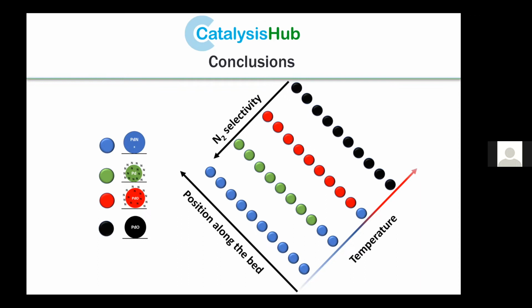Even though palladium nitride is absent from the bulk of the particle, we suggest the presence of a surface nitride structure. And while nitrogen is still present, there is still appreciable selectivity toward nitrogen. As the particle becomes more oxidized, there is a change of selectivity toward NOx product. And at 400 degrees in particular, there is a suggestion that not only ammonia selective catalytic oxidation is happening, but